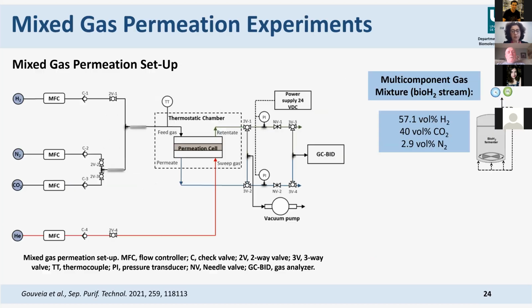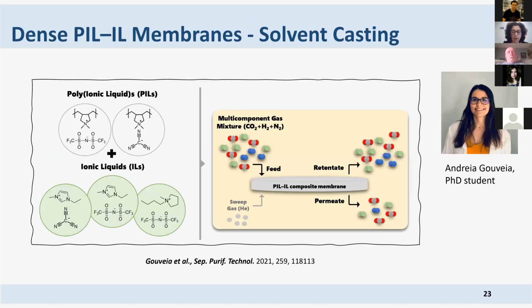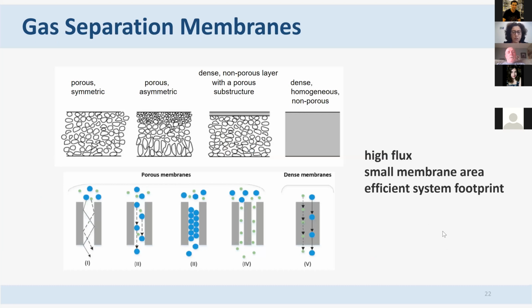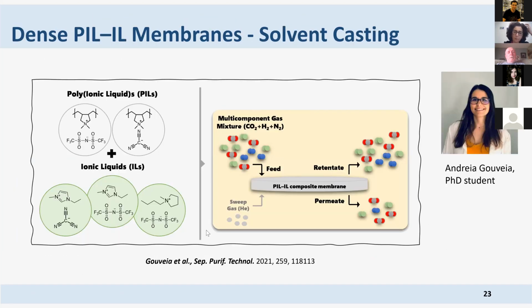So the work that I'm going to show now is the work of Andrea Gouveia, who is a PhD student. And this is part of the work that she has been doing. She has been working on the separation of biohydrogen. This work is supported on previous work from other students. And so she uses the best polymeric ionic liquids that we were able to prepare and dopes them with 40% or 60% of ionic liquid so that we have a better flux and the plasticizing effect on the polymeric ionic liquid that we need.